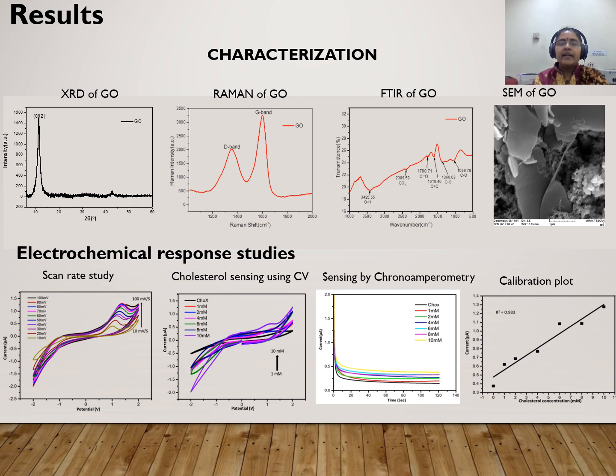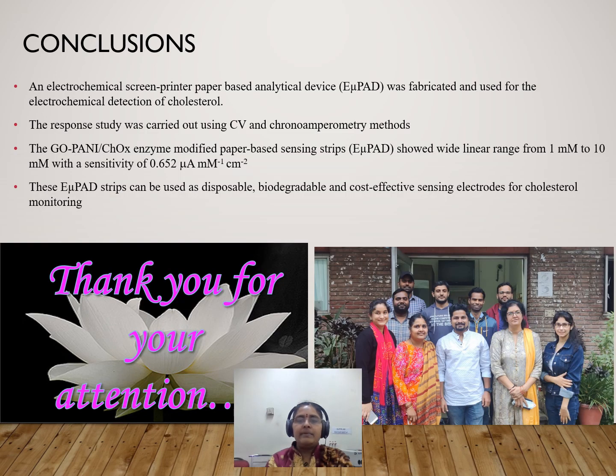And further, we have taken the chronoamperometry studies also at different concentrations of cholesterol, and again the increasing trend of the current is observed as shown in this figure, and the calibration plot was made using these values of the peak current. The calibration plot showed a good linearity, and the sensitivity was calculated using the calibration plot, and it was obtained to be 0.652 microampere millimole inverse centimeter to the power of minus 2. So it showed a very good sensitivity, and the electrochemical screen printed paper based analytical device was fabricated.